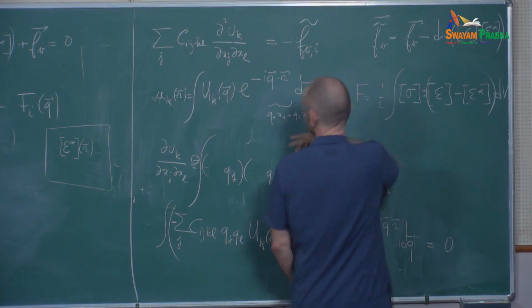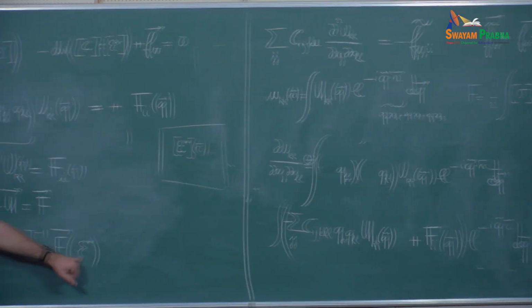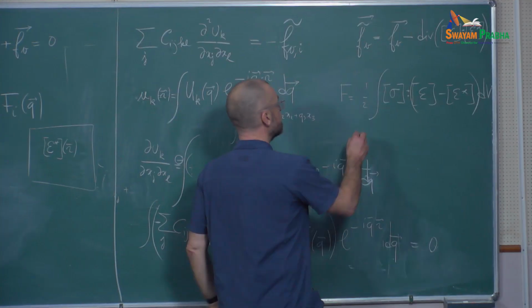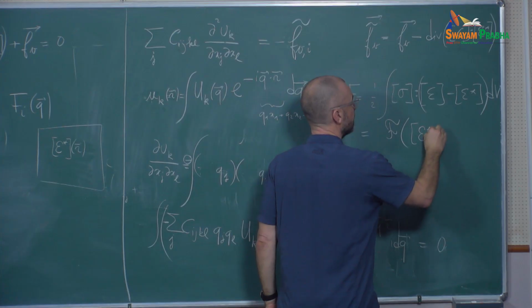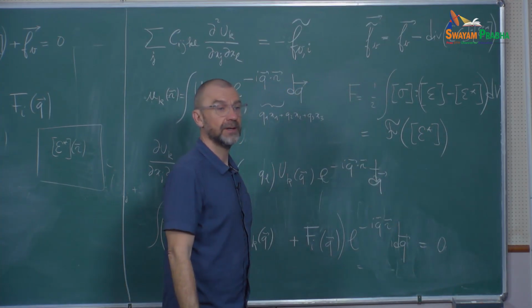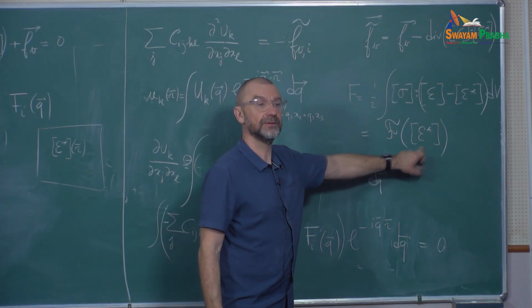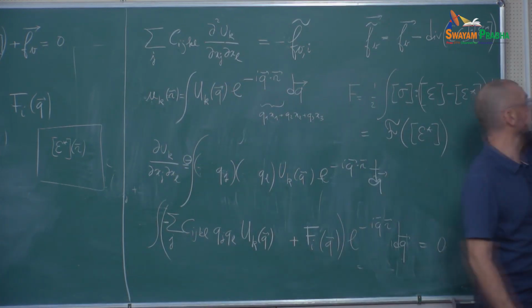When you solve for the equilibrium, the displacement becomes a function of epsilon star. So everything is a function of epsilon star, and this whole thing becomes a function of epsilon star. Now you can take a derivative of that function with respect to the different terms, and that will give you a driving force. And that's what is implemented in here.